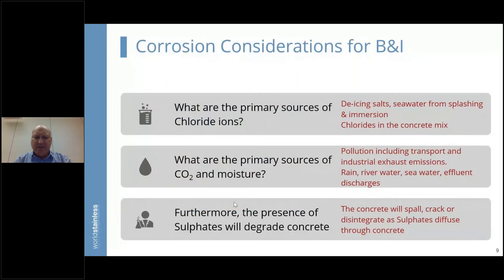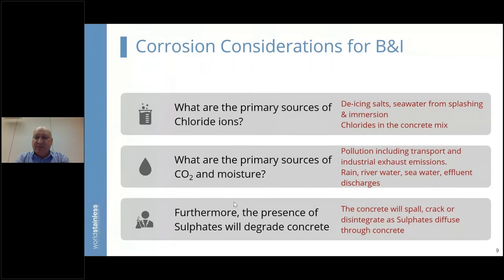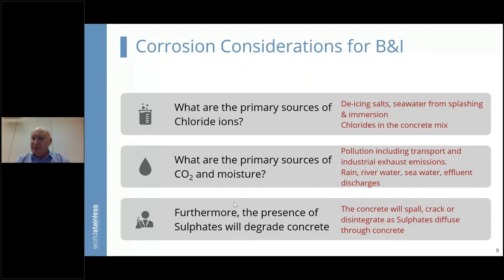Where do the chloride ions come from? They come from a number of sources: prolonged use of de-icing salt in regions above the snow line; seawater — whether from wave splash or direct immersion of structures; and chlorides in the concrete mix itself, which have often been used as part of the input products. Without carbon dioxide and the moisture that accompanies it, the chlorides don't actually attack the reinforcing bar.